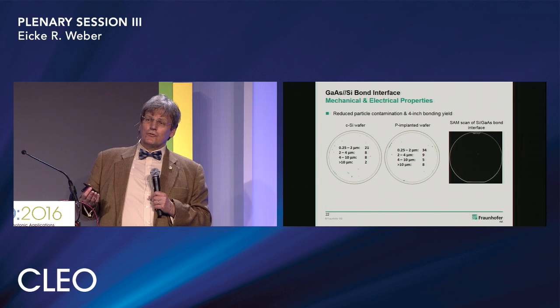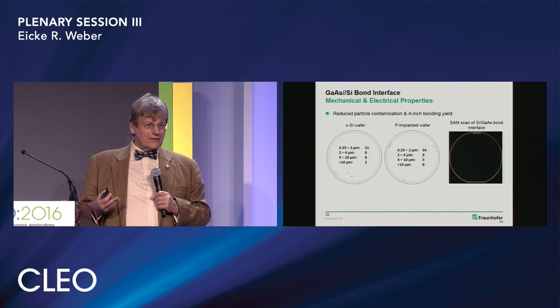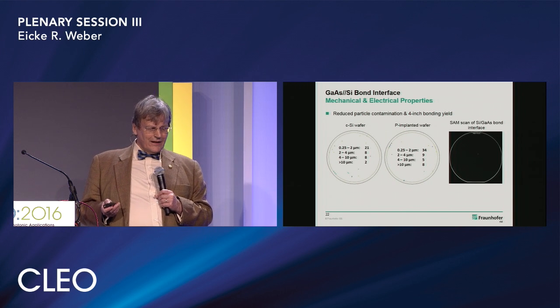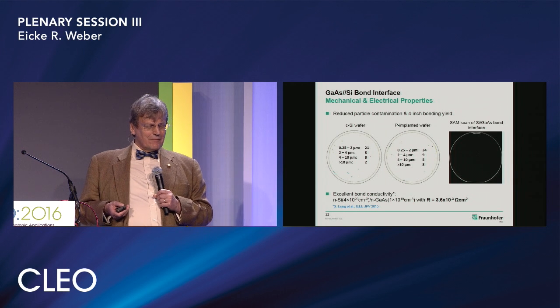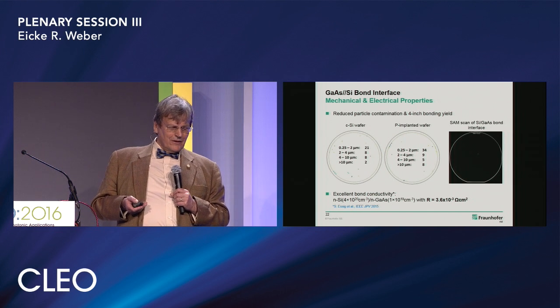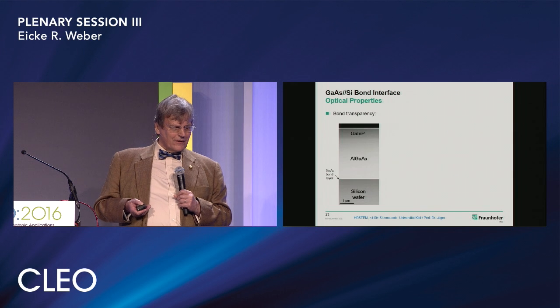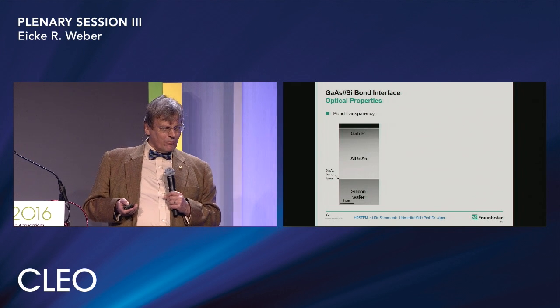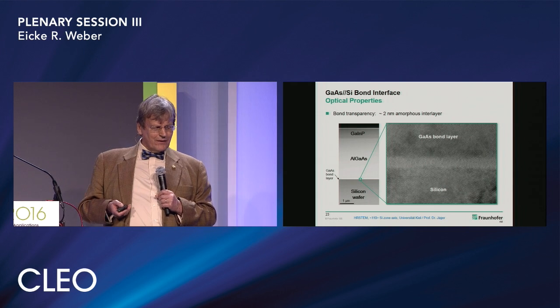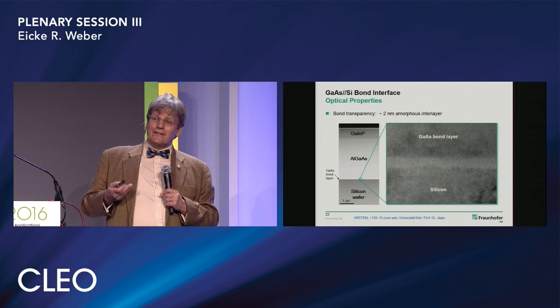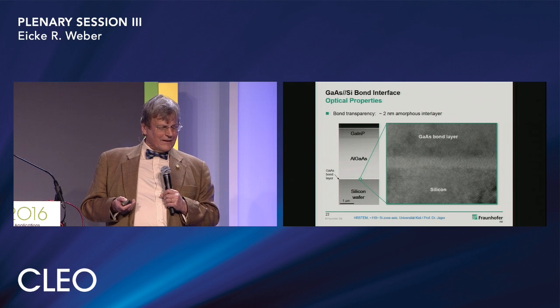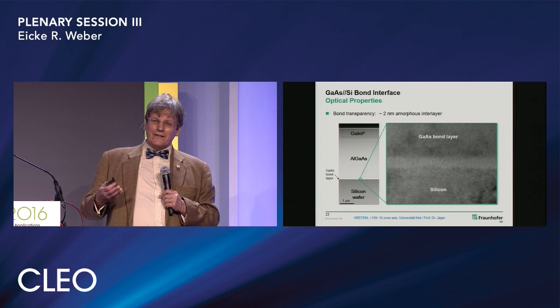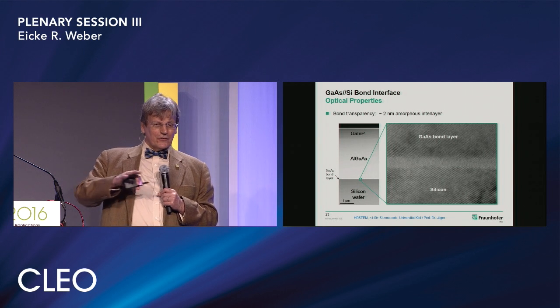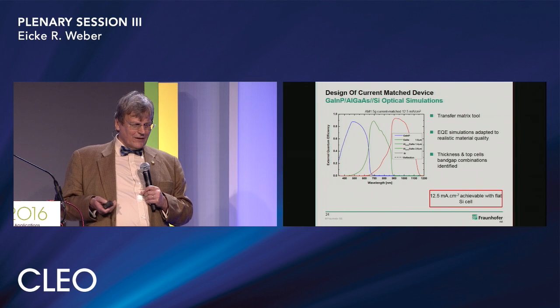The key is, of course, to do this with the utmost cleanliness, because particles and moisture are really very dangerous and very difficult. And you can measure it by measuring the conductivity through the interface. 3 times 10 to the minus 3 ohm square centimeter is a very good value for this. And you can look at the quality of the bond. This is a picture similar to the one you saw before, where the interface, which is artificially bonded together, is really a quite perfect interface. Again, I was proven wrong. A man-made interface can today be good enough to let the minority carriers come through without big losses.